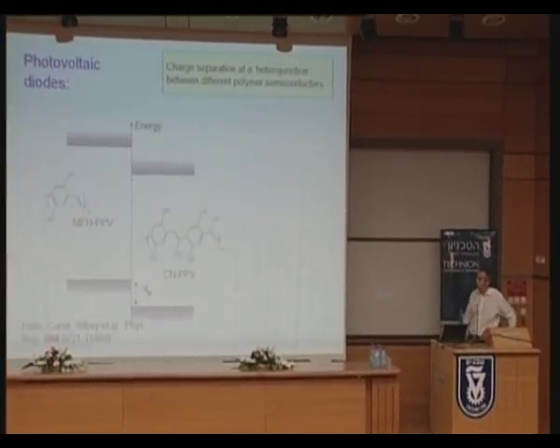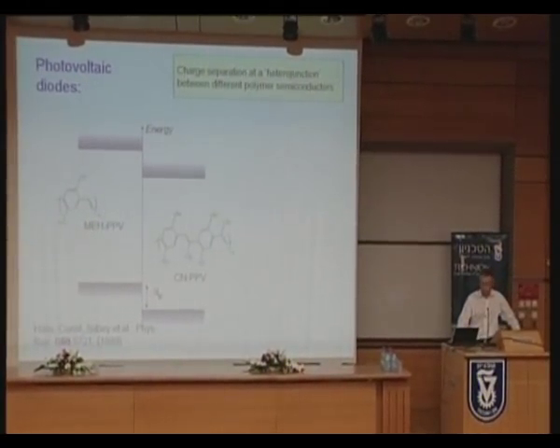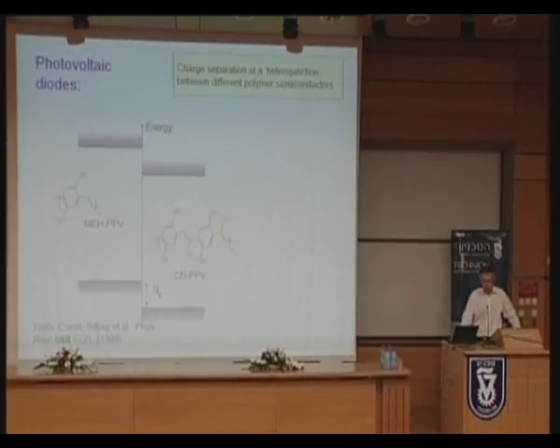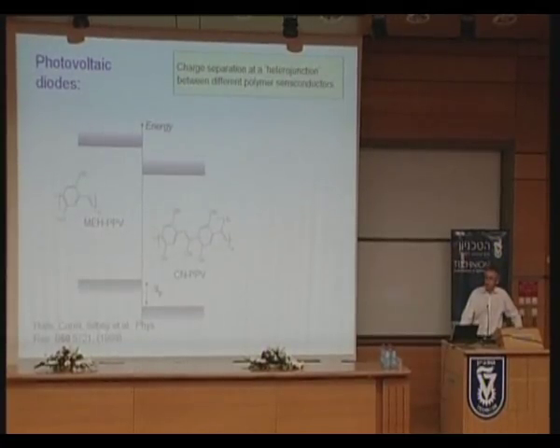So to split it up, what is needed is a heterojunction. And of course, heterojunctions are what make photosynthesis work. And heterojunctions with molecular materials are much cheaper to make than they are with inorganic III-V semiconductors. You do not need an MBE machine to grow clean structures. All you need to do is mix together different materials. And because there are no broken bonds at interfaces, we just pile them up one on the other, and we can get a clean interface.